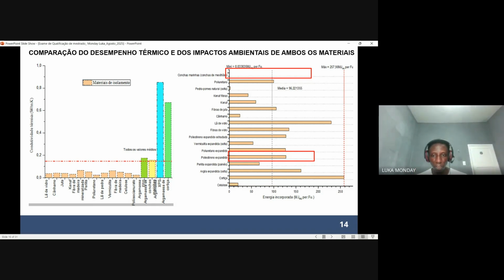What the research tends to achieve is to diminish the thermal conductivity of each of these materials. But expandable cork and extruded polystyrene have a higher thermal conductivity compared to the likes of seashell mortar and EPS mortar. However, most of the traditional insulation materials have a thermal conductivity below that of expandable polystyrene and seashell. However, most of these materials are expensive, and they also have a water accessibility aspect, whereby water tends to penetrate into these materials, and they are difficult at times to find in the market.